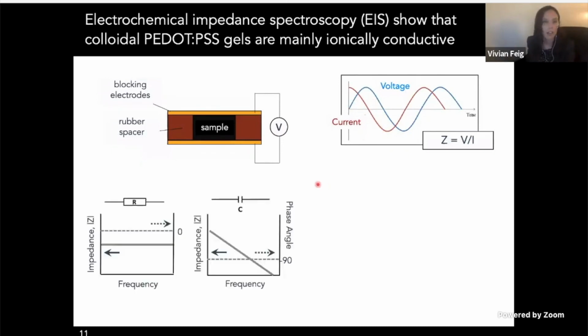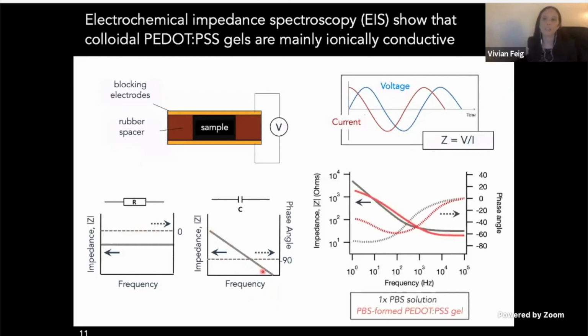And really briefly, what you can tell from these sorts of measurements is that if your measurement circuit is looking like a resistor, then you'll have a frequency independent impedance with a phase shift of 0, whereas if it's more like a capacitor, you'll have a frequency dependent impedance and a phase shift of -90. So if we do the same type of measurement with our gel, then here in the pink, we see that the impedance profile basically resembles that of just a purely ionically conductive PBS electrolyte.